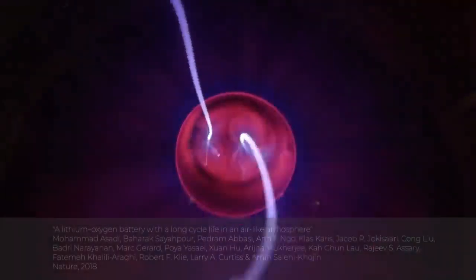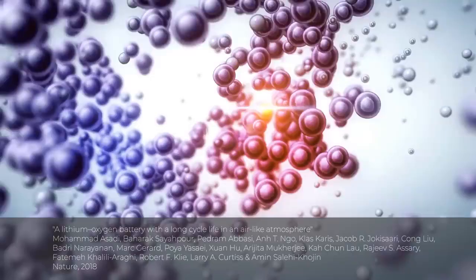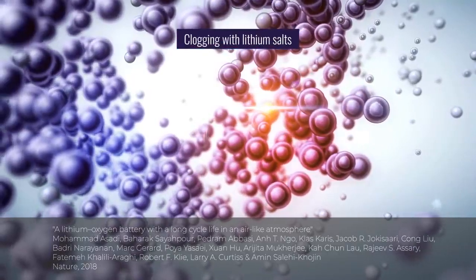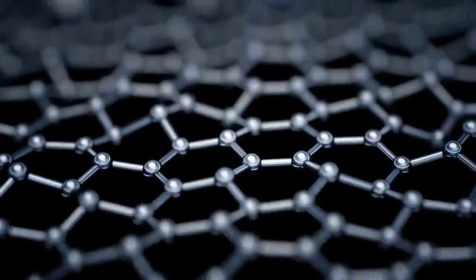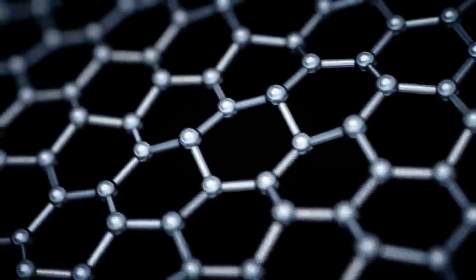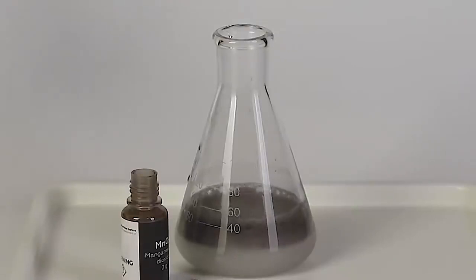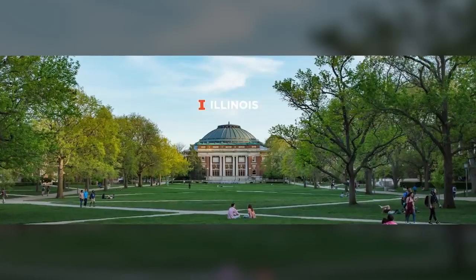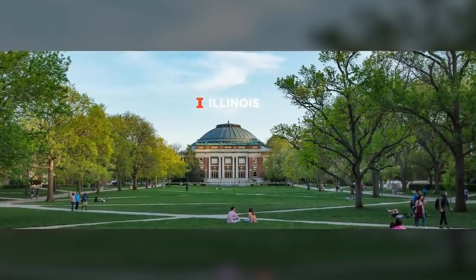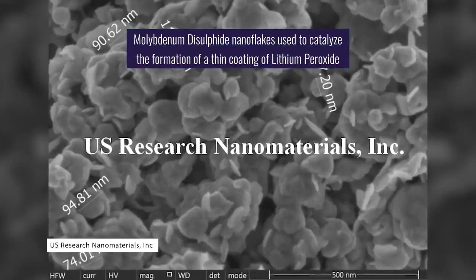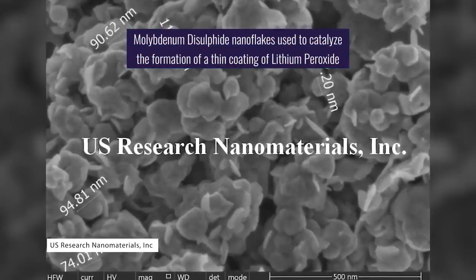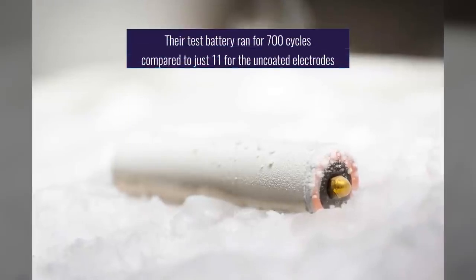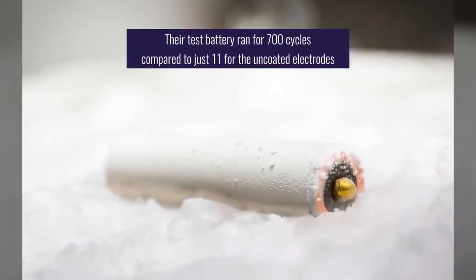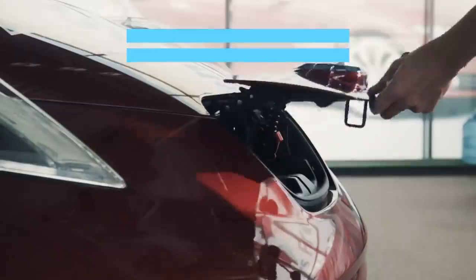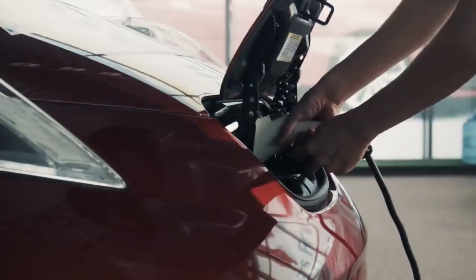As usual, this technology is not without its drawbacks. Current electrodes of lithium air batteries tend to clog with lithium salts after only a few tens of cycles. Most researchers are using porous forms of carbon to transmit air to the liquid electrolytes. Feeding pure oxygen to the batteries is one solution, but it's a potential safety hazard in the automotive environment. Researchers at the University of Illinois found that they could prevent this clogging by using molybdenum disulfide nanoflakes to catalyze the formation of a thin coating of lithium peroxide on the electrodes. Their test battery ran for 700 cycles, compared to just 11 cycles of an equivalent with an uncoated electrode. While this isn't enough lifetime for a car, it's a promising hint of things to come.